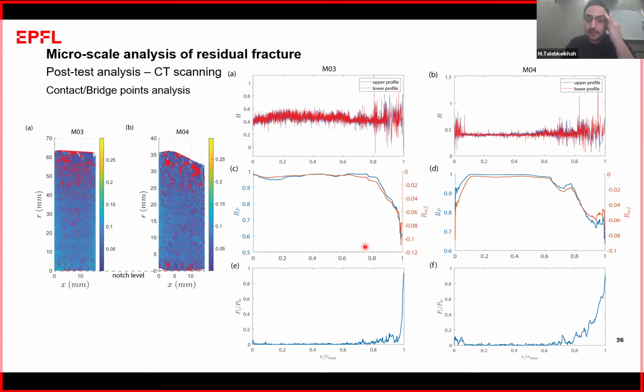And in parallel, we also calculated the autocorrelation, the Pearson correlation value that we all know as R square, and also the autocorrelation decaying slope. The Pearson correlation coefficient, exactly when we reach this process zone, deviates from the value one, which shows that the correlation decreases. And the decaying slope of the autocorrelation increases in the negative range. This means that the correlation between two surfaces vanishes faster, exactly when we have this process zone.